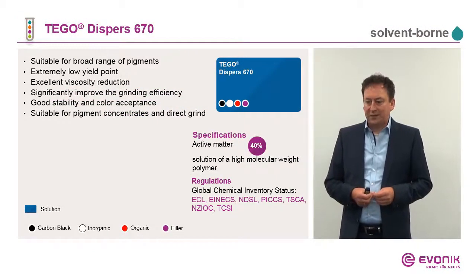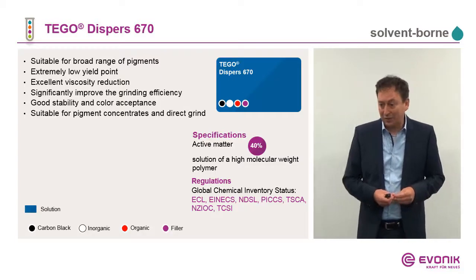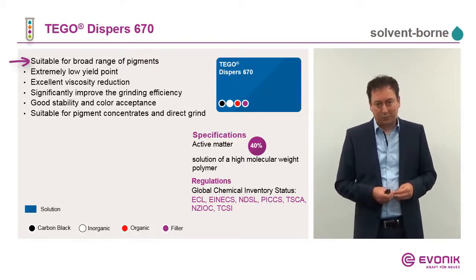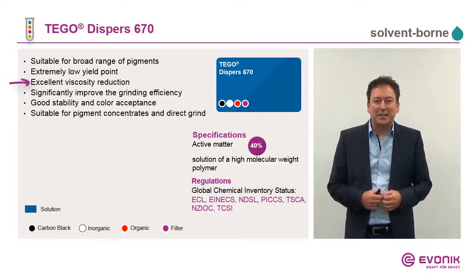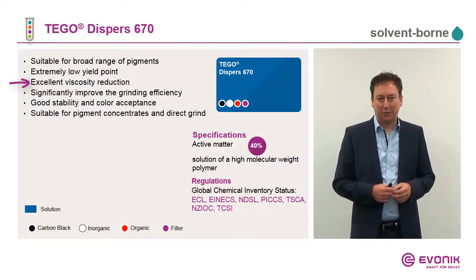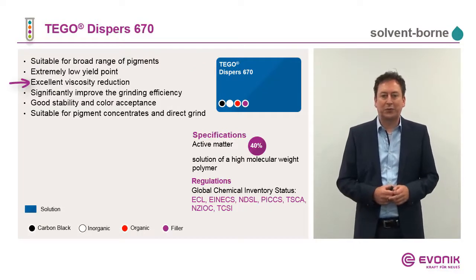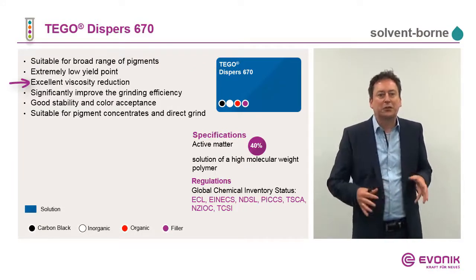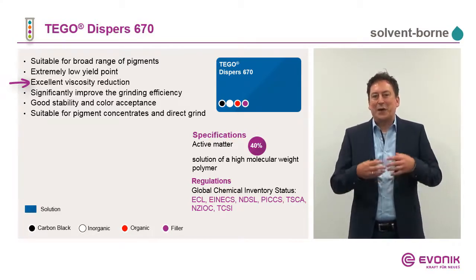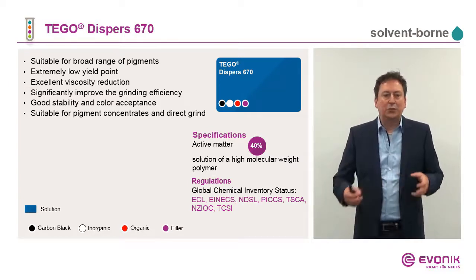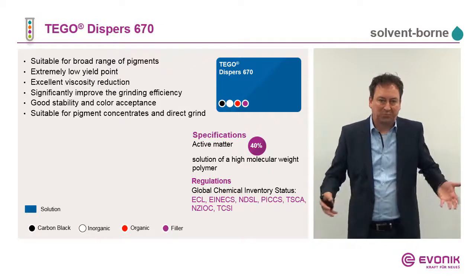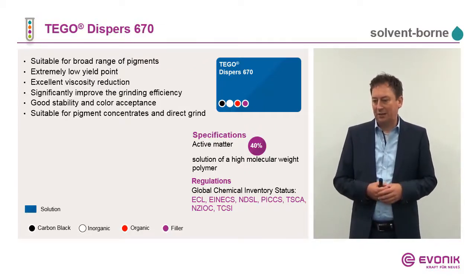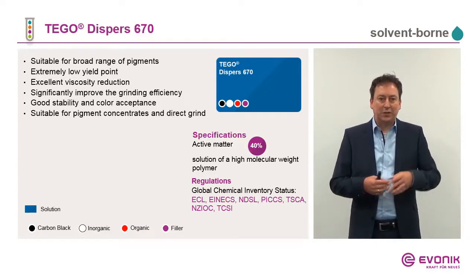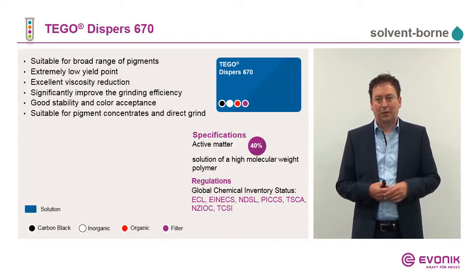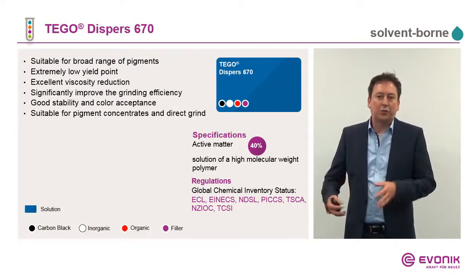The TEGO Dispers 670 here, mentioned as a highlight, is suitable for all pigment types. You will see the outstanding viscosity reduction of TEGO Dispers 670 with inorganic pigments. It gives very strong viscosity reduction with inorganic pigments, and because of that, the customers usually know it because it is the outstanding viscosity reduction. It can be used for all kinds of pigments in all fields of application. Really a highlight. Active matter is 40%. It is diluted in MPA and DBE. DBE in some countries does not count as VOC. Also here you can use it sometimes for low VOC colorants.